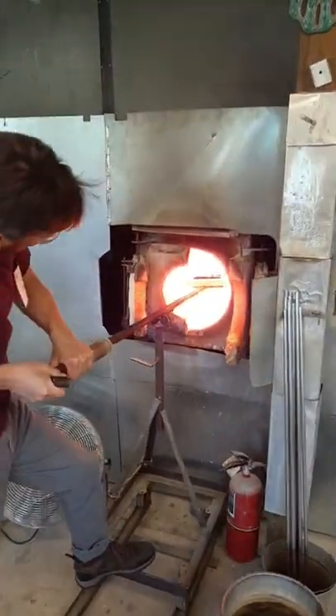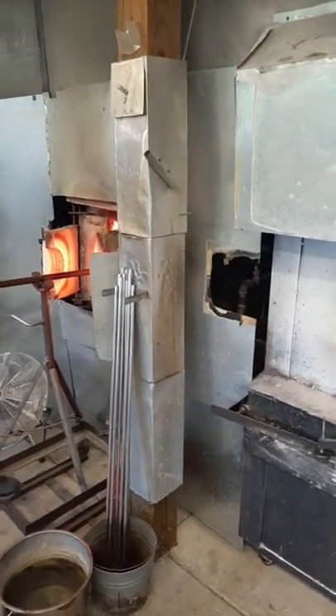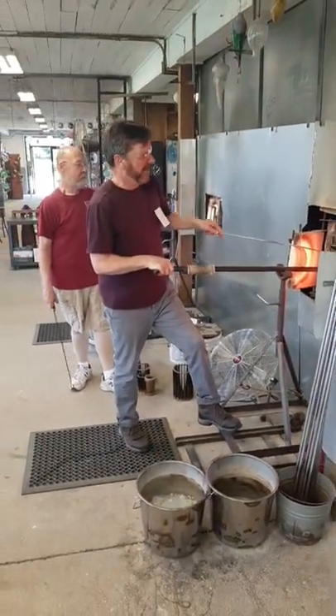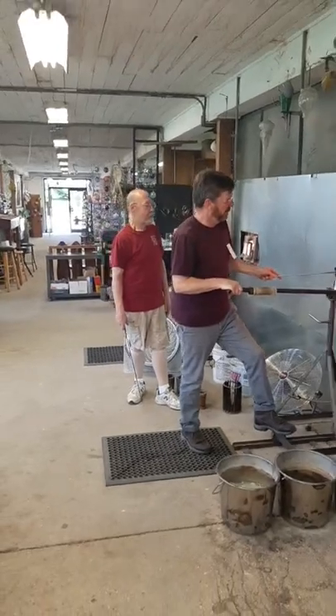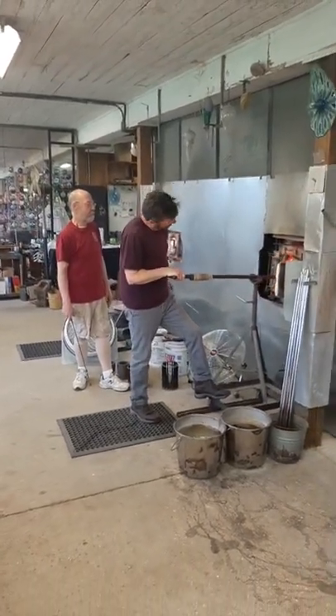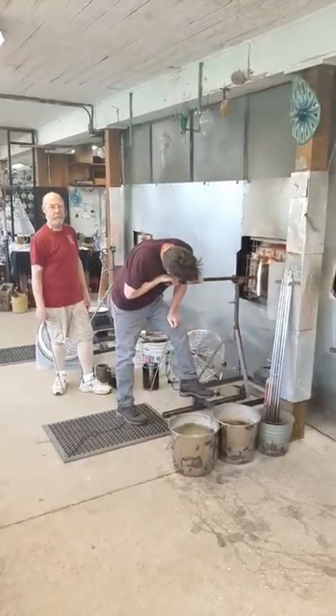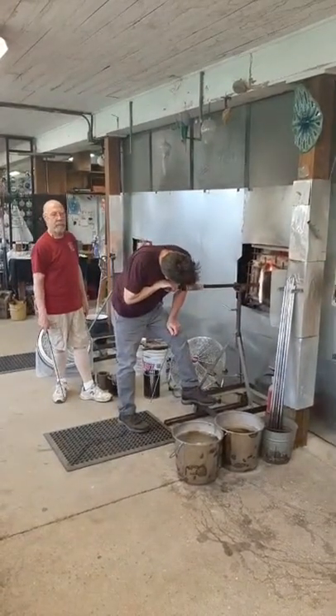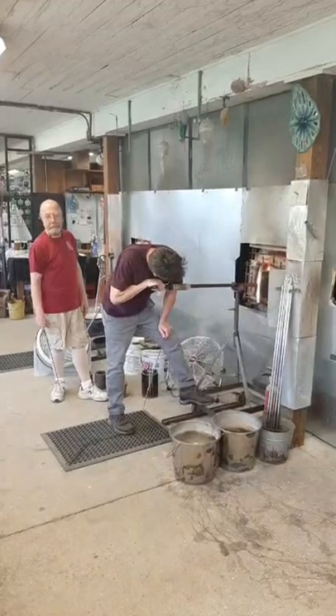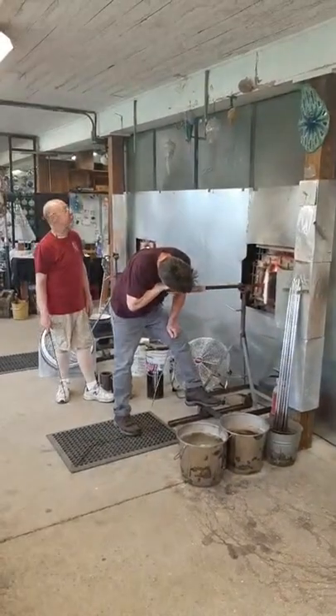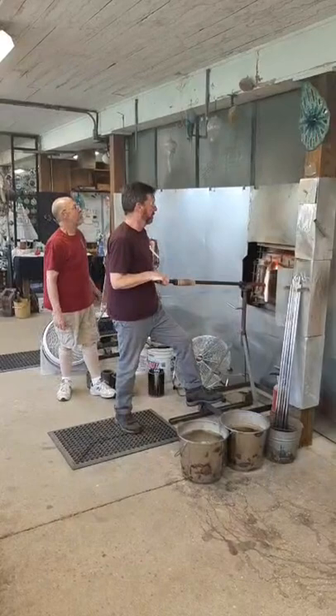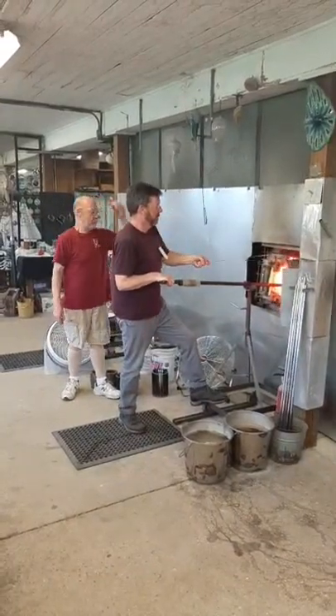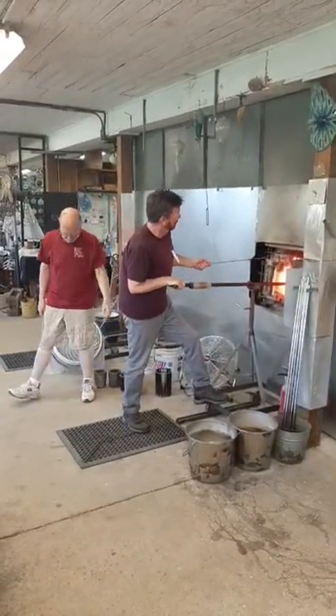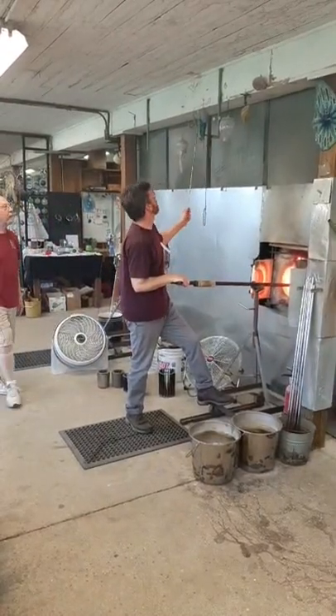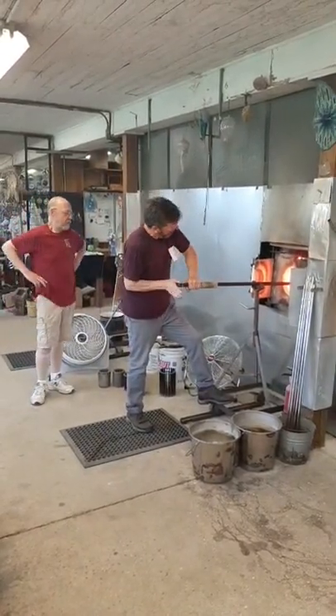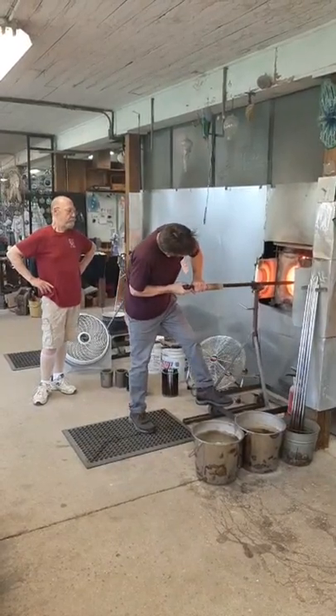These murrini will have to get to a temperature of somewhere probably around 1800 degrees Fahrenheit. At about 1300 they'll start fusing. And he may not have to go all the way to 1800. He could probably get away with a little less temperature than that, but the idea is he doesn't want all those little half-inch squares to come apart when he goes to roll them up. So they will be fused together and they will be a continuous sheet then. And when he rolls the collar across that he made, that will pick up the glass and he will form a tube on the end of the blowing iron.